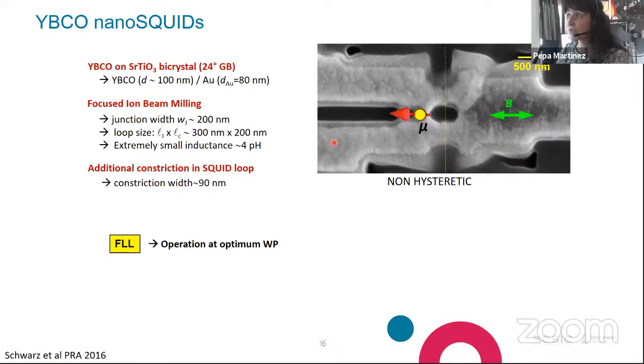This is a SEM image of a typical device. Additionally, we pattern a small constriction here that allows us to flow a modulation current through, that can couple a net magnetic flux through the nanoloop. This is very useful for characterizing the devices, but also to operate them at an optimum working point. Since the voltage response of a SQUID is phi-zero periodic, this constriction allows us to operate the SQUID in a flux-locked loop mode, so at a fixed flux position.